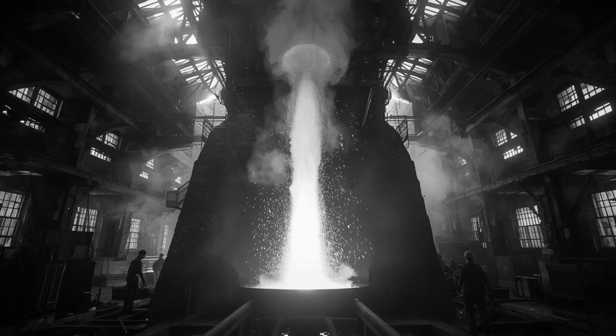The refractory quality comes under scrutiny. Perhaps the bricks installed during original construction were of inconsistent quality, causing one side to insulate better than the other. The masons pull samples from both zones. Laboratory analysis shows identical composition, identical porosity, identical thermal properties. The brick isn't the variable.